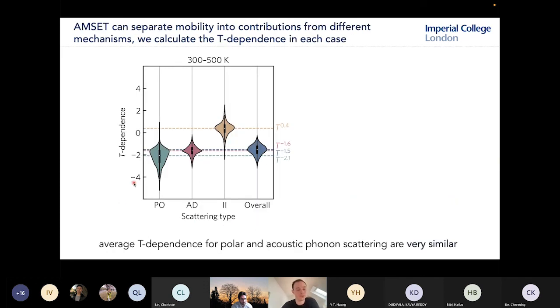And this is just a summary of the results. Here I'm showing the temperature dependence limited by different scattering mechanisms; polar optical and acoustic deformation potential I'll discuss now. There are two points that I want to make. The first is that these are violin plots, which effectively show a histogram of the results. The distribution for polar optical phonon scattering and the acoustic deformation potential distribution overlap entirely. If you had to pick a point in here, you wouldn't be able to distinguish which one it was in. The second thing is that the average temperature dependence across the entire distribution is very similar. For polar optical phonon scattering, it's minus 2.1, and for acoustic deformation potential scattering, it's minus 1.6.